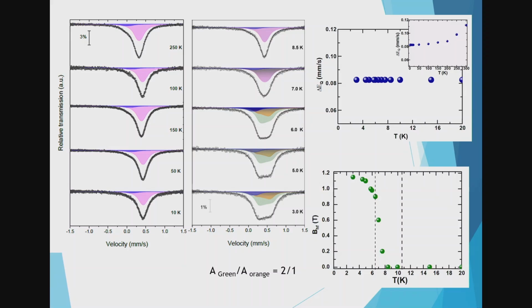And now I'm working with Mariela. Mariela had the idea to make the fittings keeping the quadrupole splitting constant, as it should be, and she introduced two subspectra. I just want to call your attention to this line here, which is maybe some small impurity in this sample, or maybe some iron that is going to the germanium site, which is also known for this kind of materials. Sometimes when you dope with iron, it prefers to be in the ruthenium and germanium sites, and then there may be some iron going to the germanium site, and it's not bothering the rest of the fittings too much, okay? So again, we did the fittings, and she's using two components here to fit this spectra, okay?